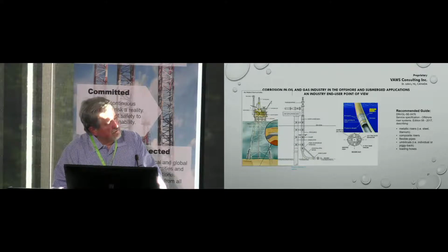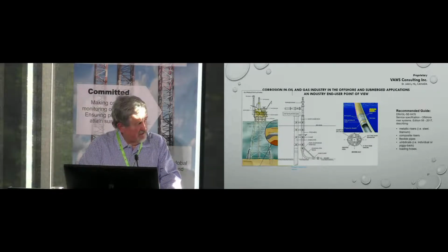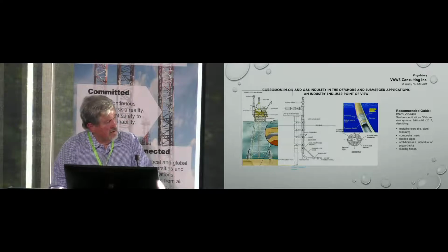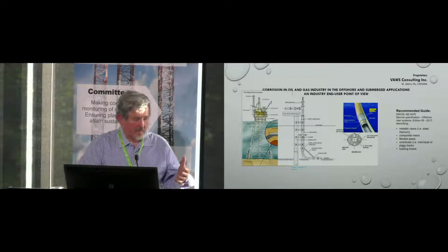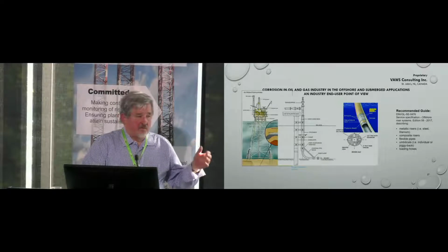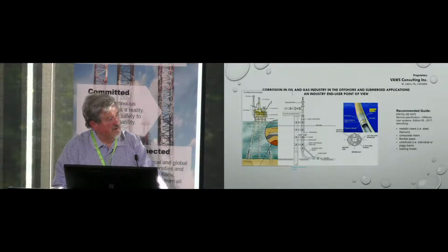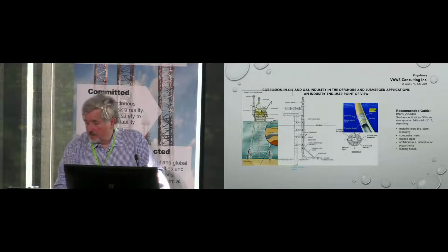The new methods on the very right, the flexible lines, are relatively new technology, and we are still learning about it because there were some reported failures. I worked with liners for pipelines in Alberta at the beginning of my career, and that was a great thing at the time. But with most of these plastics, gas can permeate through them and form bubbles between the steel and the liner, and the liner can collapse, and that's a bad thing because usually you cannot turn it back.